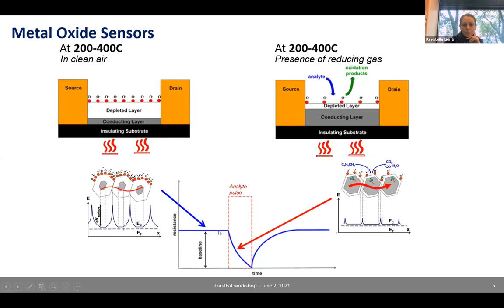And then when we have a gas analyte that comes next to our MOS, we are going to have some redox reactions between this analyte and the oxygen absorbed at the surface of the MOS. For example, in the case of a reducing gas, we're going to consume these oxygen ions. So the depleted layer is going to be thinner, and that's going to be translated in a decrease in resistance. So when we see a change in resistance of our MOS, we know that the MOS has reacted with something and has identified a gas around. And so after the reducing gas goes away, these reactions are reversible. And so basically the resistance of the MOS is going to recover back to its baseline resistance. So this is how a MOS sensor works.